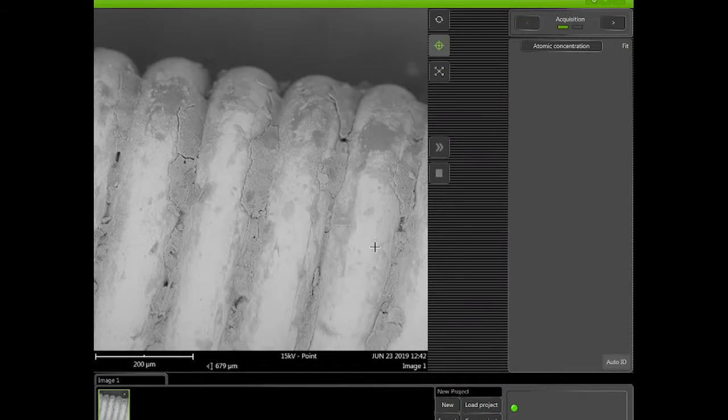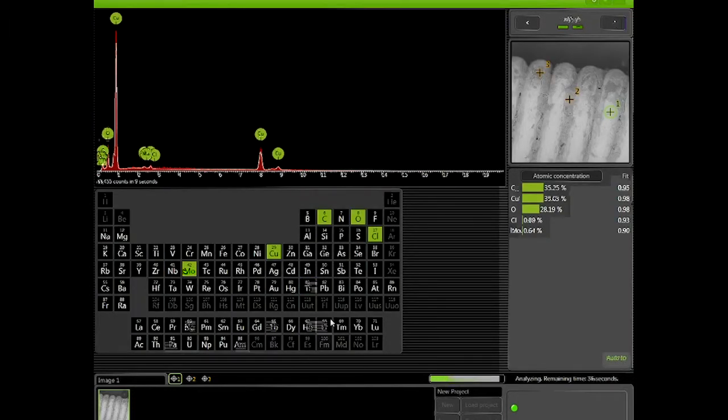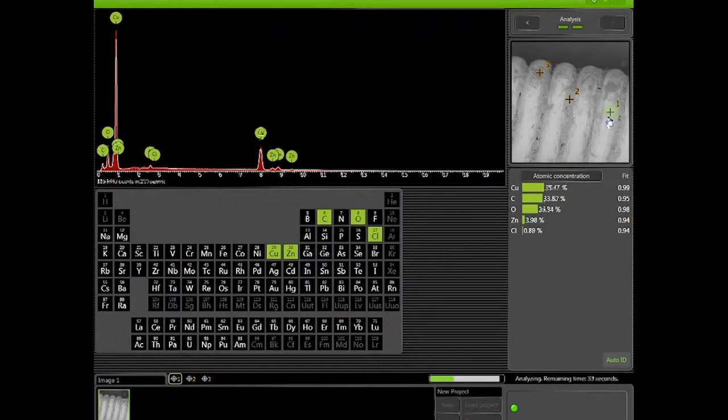We are now going to look at the EDS analysis of a copper wire sample. The EDS acquires the image from the SEM. Sorry if you see any glitches in the screen capture system. We will pick a few points for the electron beam to focus on the sample and analyze the X-rays produced at those points. The darker area indicates higher oxidation of copper, as oxygen is lighter than copper and appears darker on the image. So we can see different elements popping up, and this is the EDS spectrum, which is a plot of X-ray counts coming from that point in the sample versus energy.